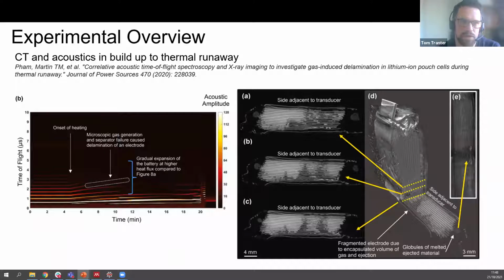So this one, for example, was an acoustic response to a cell that was undergoing thermal runaway, and this was a pouch cell. As the thermal runaway was occurring, you actually had gas generation from these reactions in the electrolyte, and this gas was pushing the layers. You would be able to see that in the lab. You'd be able to see the cell expand, but you can actually detect the onset.